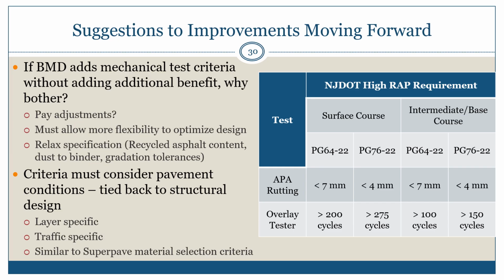tests. The other common suggestion that our interviewees made is that when criteria is selected, the agency needs to consider tying that back to some level of structural design. That obviously we need something that's extremely rut resistant in the surface for high volume traffic, but low volume in the base may not have to have the same level of rutting resistance. And so making sure that we have a tiered system very similar to what we had with our prior Superpave material selection criteria, our consensus properties, would be advantageous to the mix designer and the agency to help a system tied back to some level of structural design.